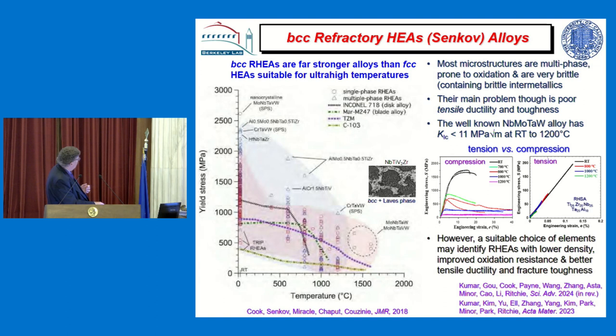Current materials sort of peak out about 1200. These materials could go up to 1600 degrees centigrade. They're interesting for things like hypersonics. They're interesting for possibly using in gas turbine engines, but they're brittle, very, very brittle. And you can see here, everybody tests them in compression, so they have good properties. If you pull them in tension, where the crack's open, the ductilities are less than 1%, less than 0.1%, whereas the previous systems I showed you had 90% ductility. So they're quite a challenge.